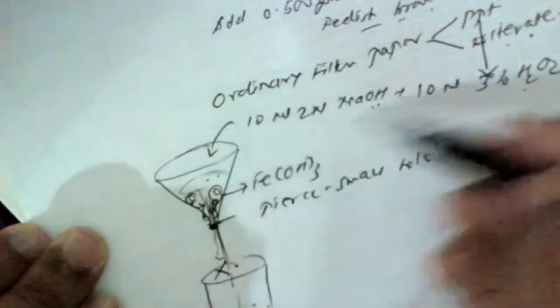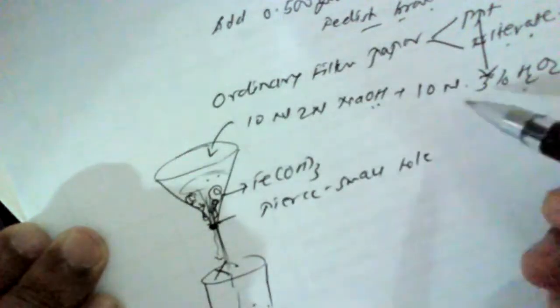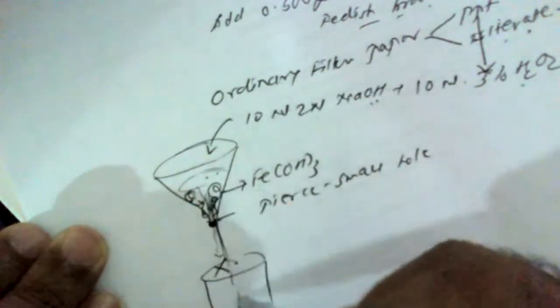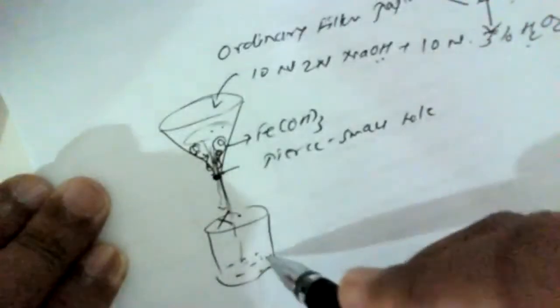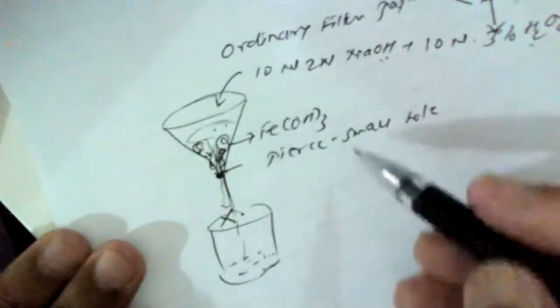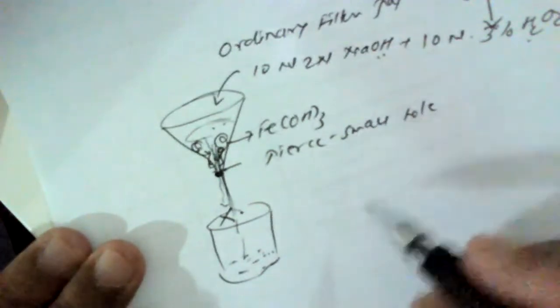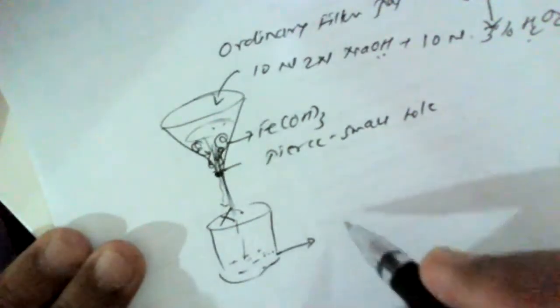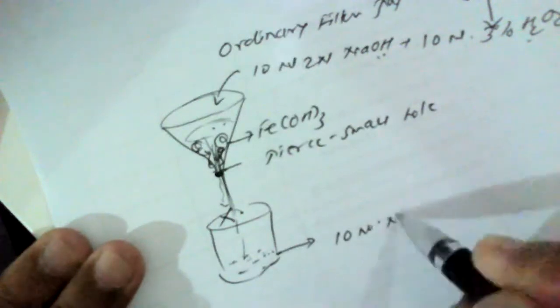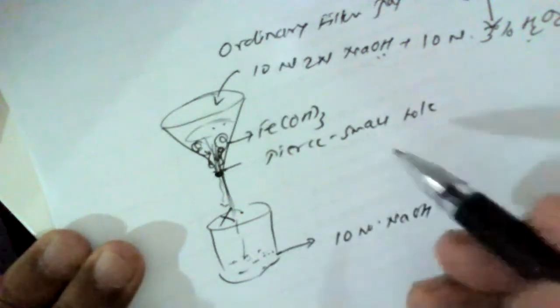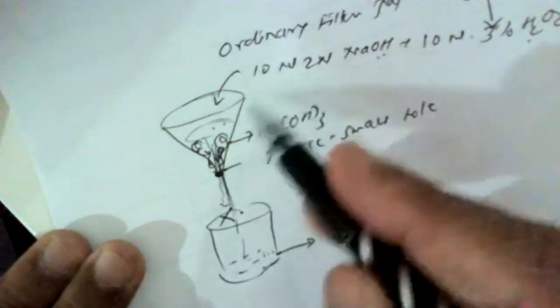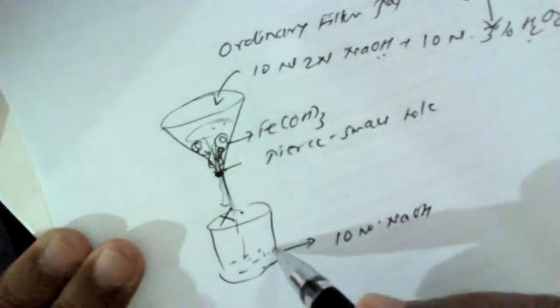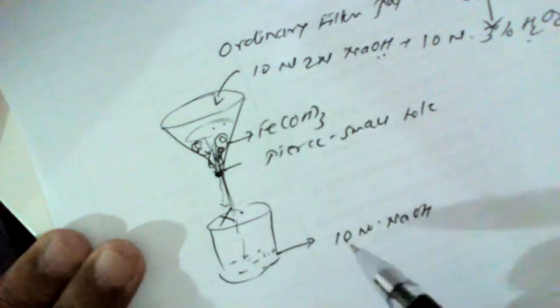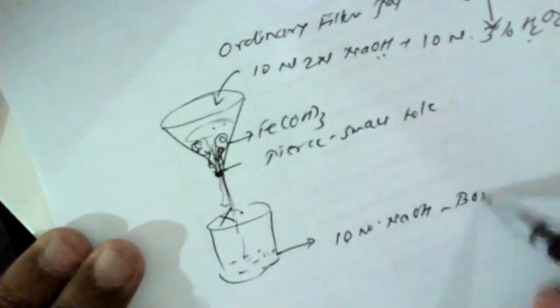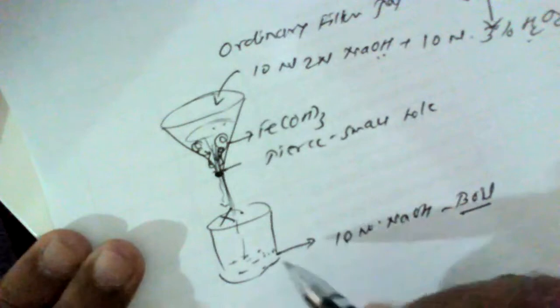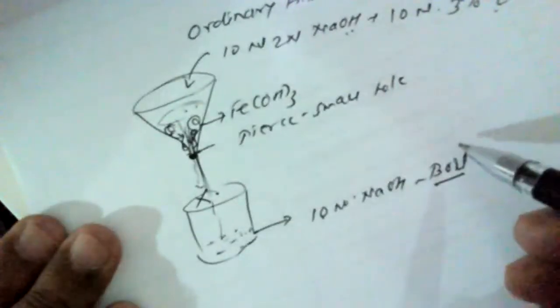So this particular washing with NaOH and hydrogen peroxide ensures that almost all the precipitate is collected in the beaker. Now, again to this beaker, 10 ml NaOH is to be added. So NaOH is to be added 2 times. First of all, for washing the precipitate. After collection of this precipitate, again we have to add NaOH, and now we have to boil this beaker by keeping the beaker on a tripod stand.